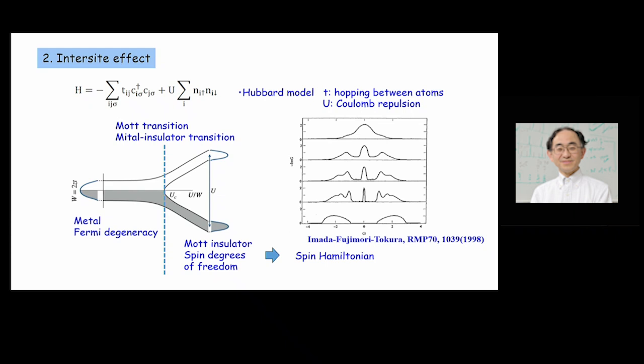This density of states corresponds to the imaginary part of the single particle Green's function, and it develops in the following way. First, you have a metallic density of states, and then some splitting of a peak appears, which corresponds to the upper Hubbard band and the lower Hubbard band, and the so-called Fermi liquid state at the Fermi energy.